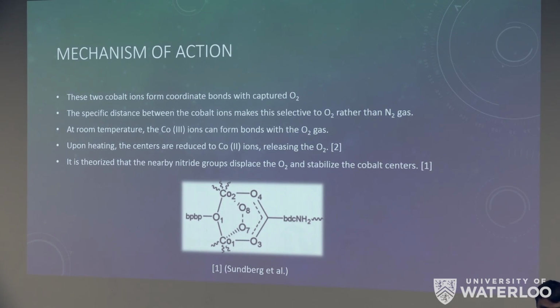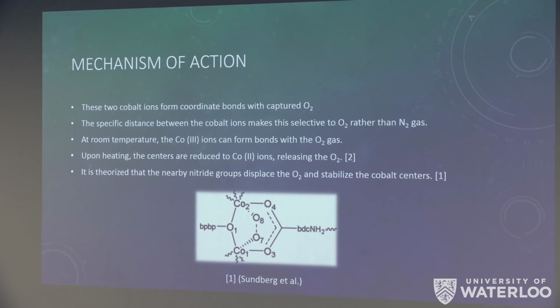So the mechanism of action, here we can see the active cobalt center. The mechanism of absorption is critically dependent on the spacing of these cobalts and the positioning of the surrounding organic ligands. This is the case with most metal organic frameworks, which show reversible gas absorption. The cobalt ions are held at the perfect distance to bind and hold this diatomic oxygen, binding O2 with great specificity rather than binding nitrogen or hydrogen, although this can be changed to produce different metal organic frameworks to absorb these other gases. At room temperature, as mentioned before, they're in the 3rd oxidation state, bonding readily with the oxygen gas.